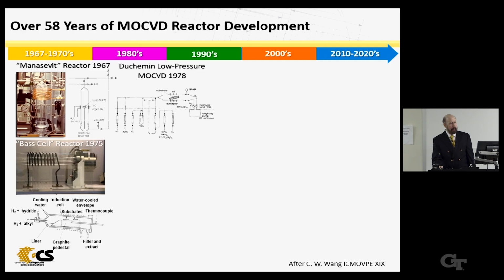A big change occurred in 1978 when Jean-Pascal Duchemin and his co-workers at Thomson CSF near Paris developed a low-pressure MOCVD. So they have a similar Bass cell, horizontal reactor, slightly tilted susceptor, but they brought their chamber to low pressure by using a vacuum pump. Interesting sub-story, the first time they did this, they pumped all the TMG out of the bubbler and into the pump because they didn't realize they had to have a pressure controller, because Duchemin had developed this process first for silicon using silane, a gas source. He wasn't familiar with liquid sources, so interesting times.